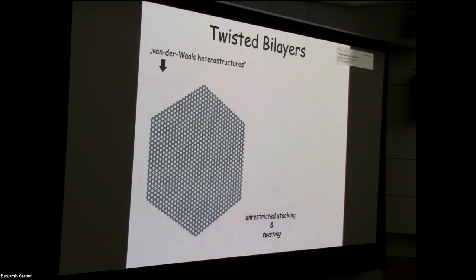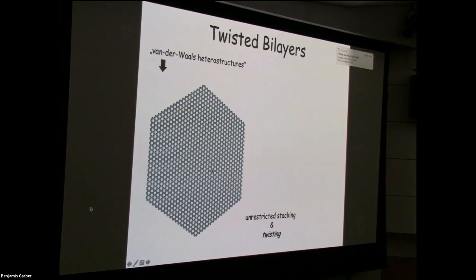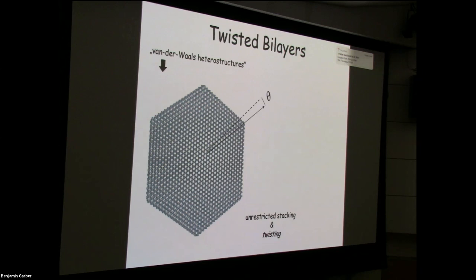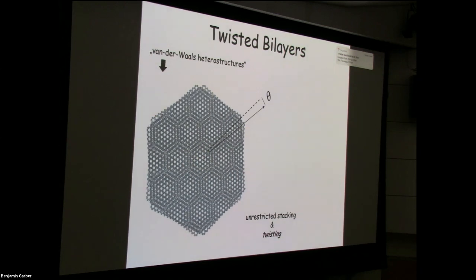So what I'm showing you now is actually two layers of two honeycomb lattices. You can only see one because they're right on top of each other. And the Moiré pattern has to do with twisting. You see there, I've twisted one layer relative to the other. A very similar effect happens if the two lattices have slightly different lattice constants. But let's stick with this case. And so you can think of two graphene layers twisted by some small angle.